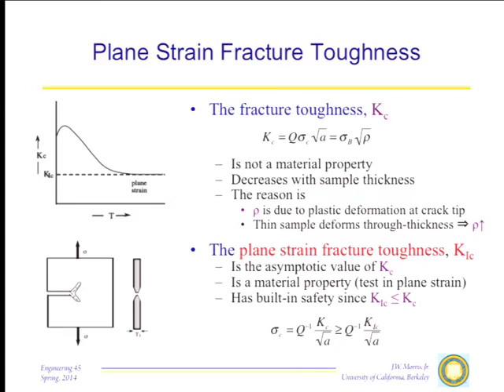What matters is that the toughness of my actual sample at any thickness cannot be less than the plane strain value. Anything that happens here will make the toughness greater. What I want to do is to calculate my breaking stress, my critical stress, the design stress, the stress I cannot reach without causing this thing to fracture for a given crack size. So let's look at that.